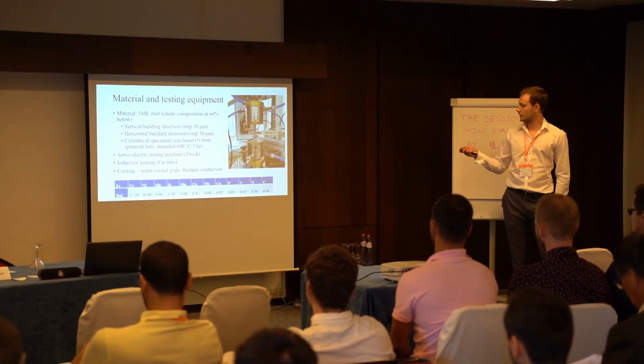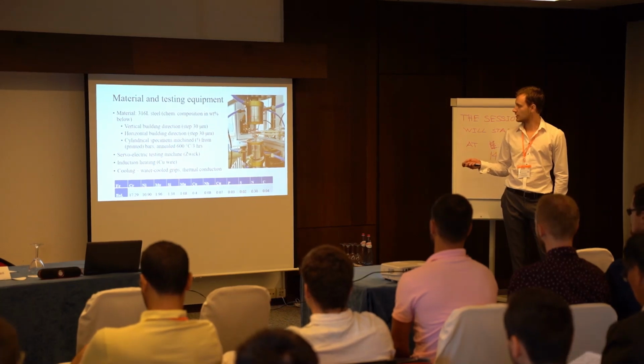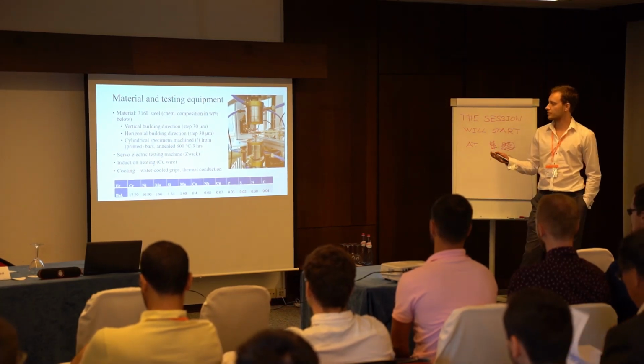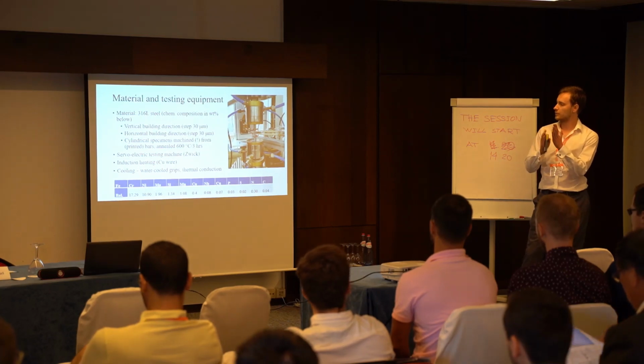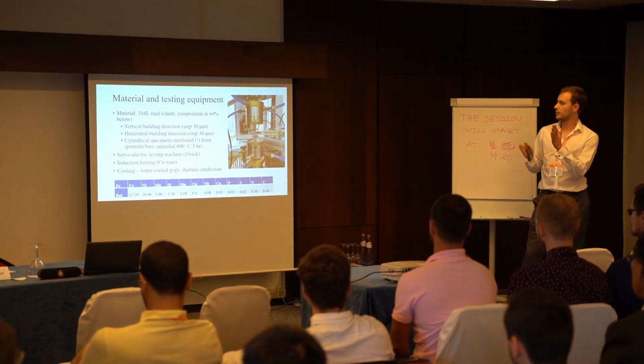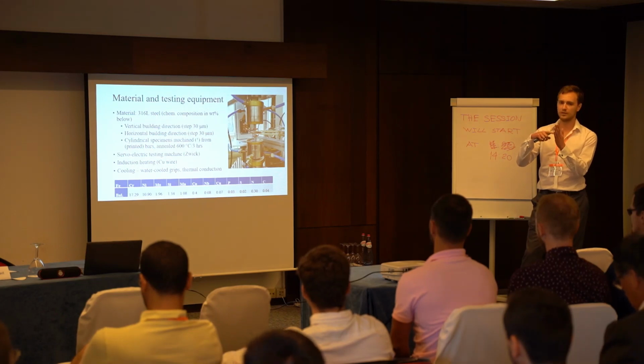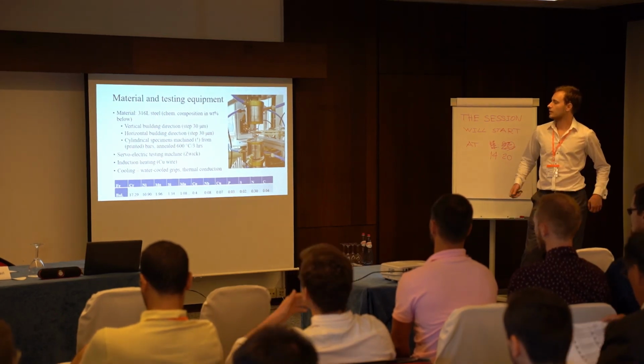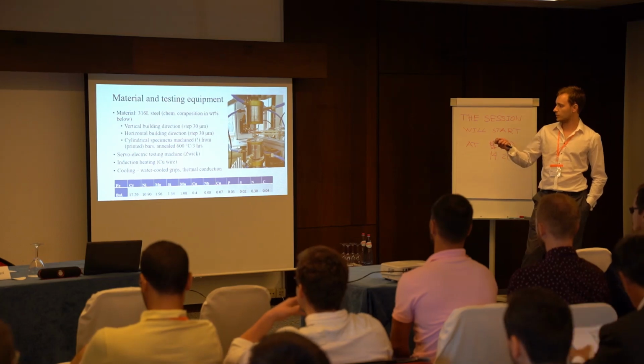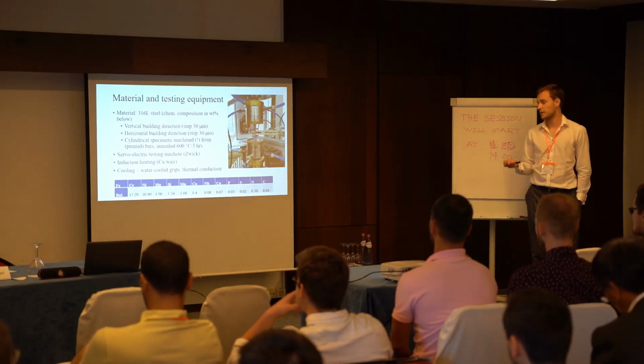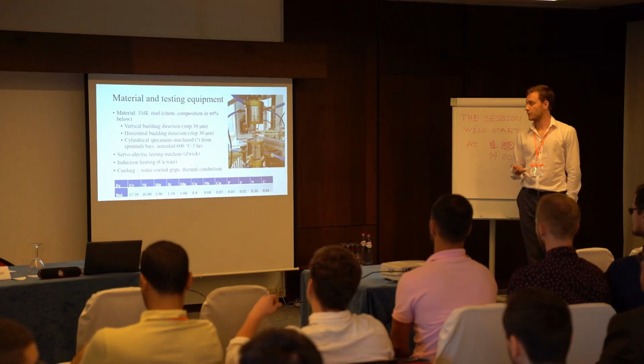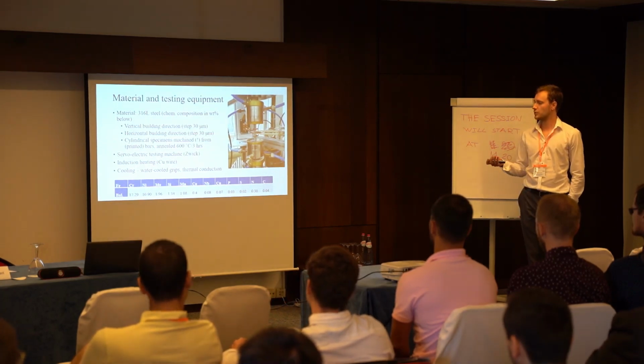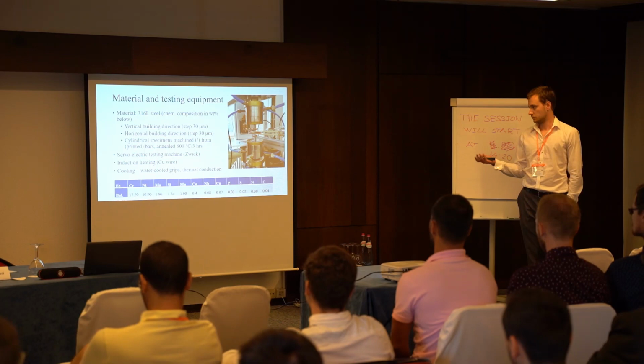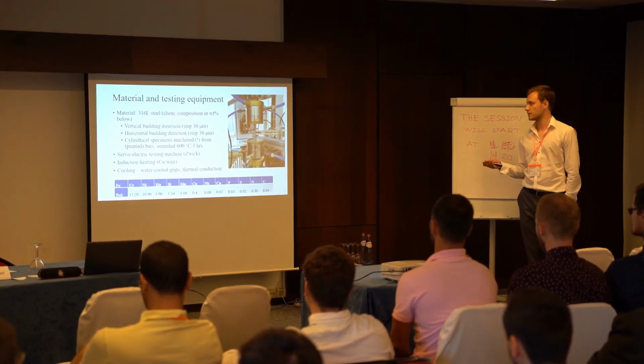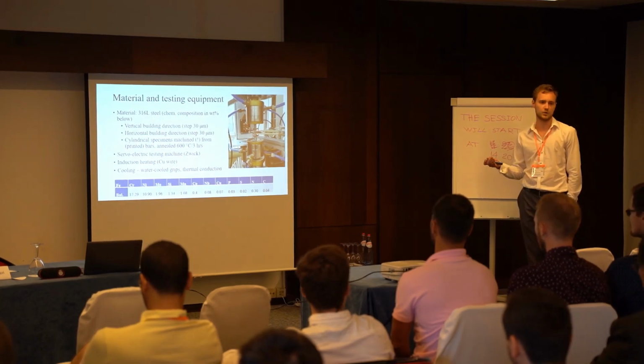We have the experimental setup here, and we see that the specimens, as they were cylindrical, means that the vertical building direction was aligned parallel to the loading axis, whereas in the case of horizontal, it was obviously 90 degrees to it. The machine we used for testing was the electric testing machine from Zwick. For varying the temperature field, we used induction heating, copper wire, and we cooled the grips with water, and of course the specimen was also naturally cooled by thermoconduction.